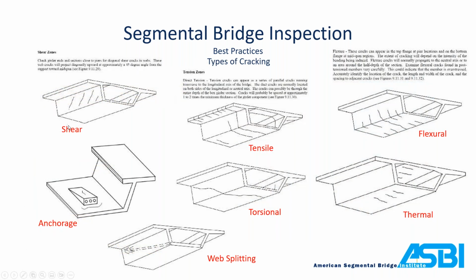So again, this is out of the BIRM. I just kind of consolidated the different cracking schemes here. So, shear cracking is going to be diagonal around your bearing areas. Tensile is going to be in your positive moment sections on the bottom of the slab, similar with the flexural. Anchorage, your segmental bridges inside will have these bump outs here where the tendons are locked off and anchored. If you don't have the required reinforcement here to support this anchorage, you could see some cracking around the anchorage.